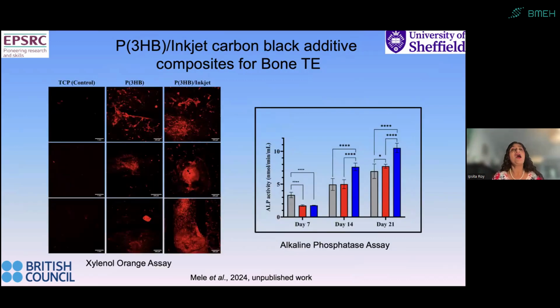Here we have further evidence. You can see that mineralization has occurred, which is important for bone. As we know, it's collagen plus hydroxyapatite. And this was a xylenol orange assay that we did and found that we got excellent mineralization in both P3HB and the inkjet composite. However, the inkjet composite was a bit better.